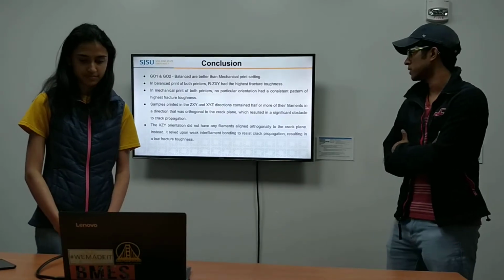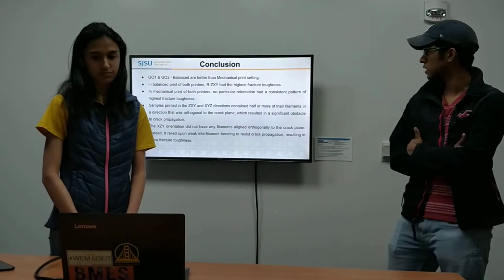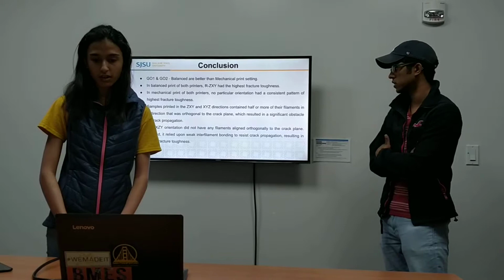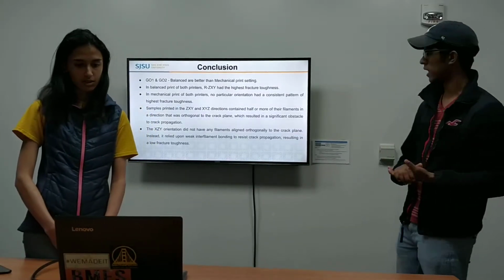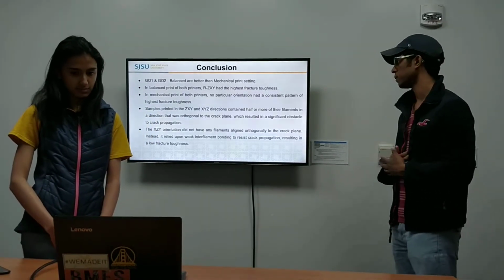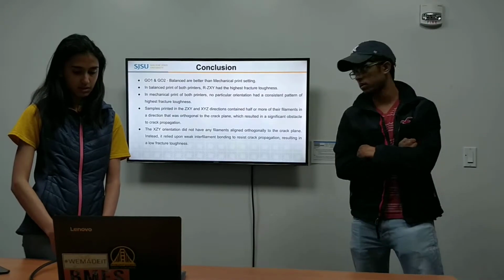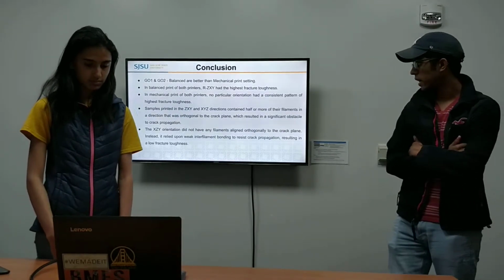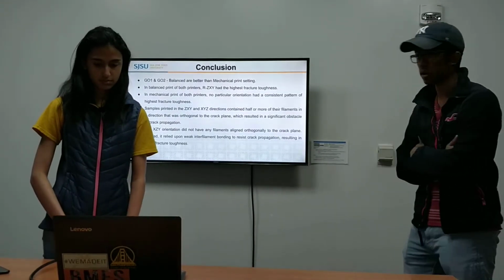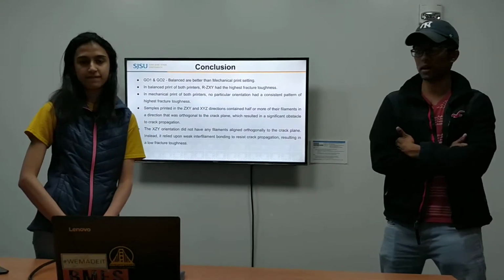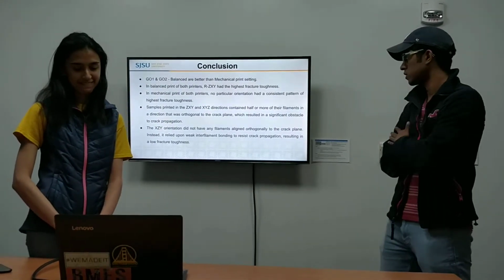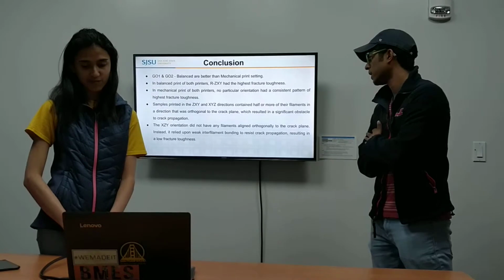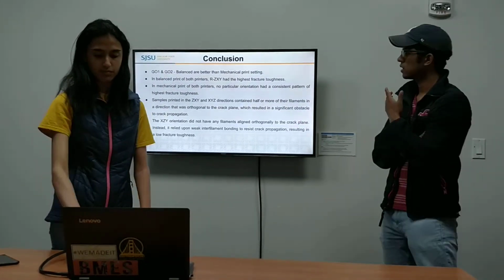Samples printed in the ZXY and XYZ directions contain half or more of their filaments in the direction orthogonal to the crack plane. So that's why we think there may have been a significant obstacle to crack propagation. And XZY did not have any filaments inside the printed part aligned orthogonally to the crack plane. That's why it had low fracture toughness.